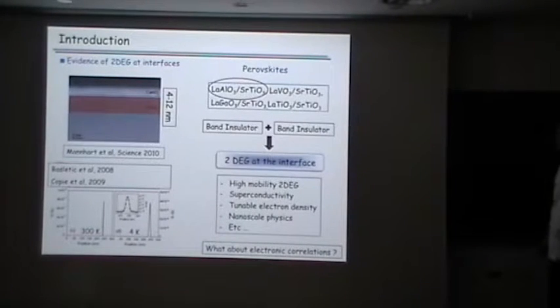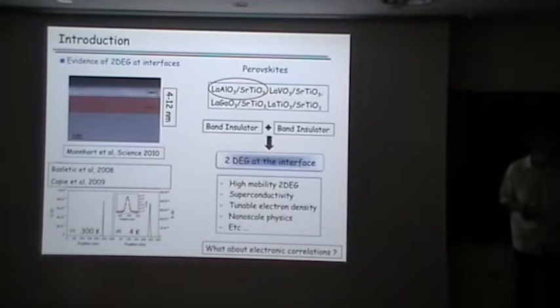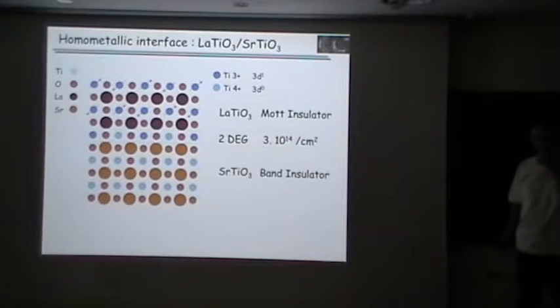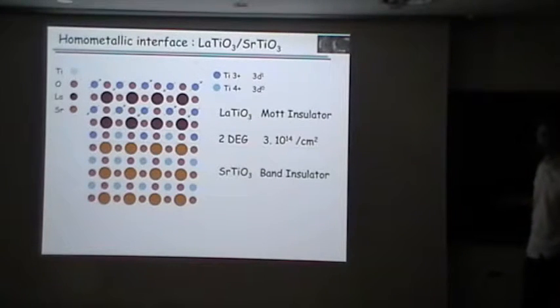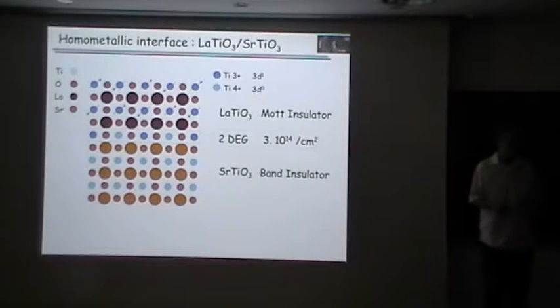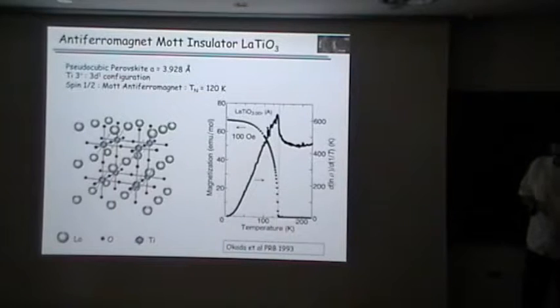So for the last part of this talk, I would like to present some results we got on the lanthanum titanate on strontium titanate system. I think this is an interesting one because lanthanum titanate is a Mott insulator. This is the only one of all those perovskites I was talking about, grown on strontium titanate, and as I explained to you yesterday, you can understand whether you can have charges in this system. The Néel temperature of lanthanum titanate is like 120 Kelvin. That means for all the low temperature experiments we'll talk about here, in principle lanthanum titanate is in the antiferromagnetic state.